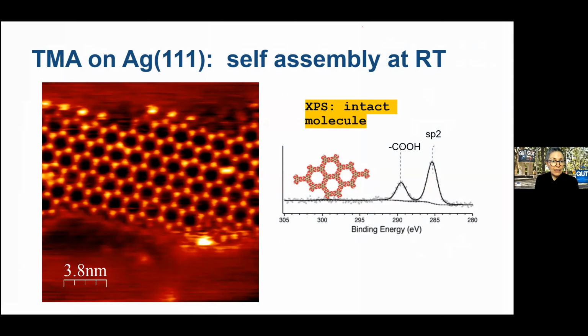We start at the beginning, though, looking at trimesic acid deposited onto silver 111 at room temperature, where we observed the formation of the same chicken wire structure that we had seen previously on graphite under a number of conditions. So we weren't the first to observe this. This was an expected result.